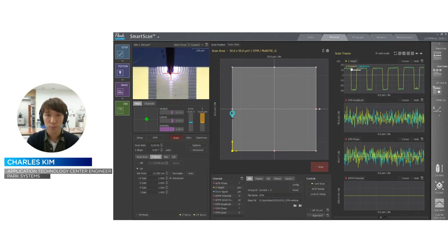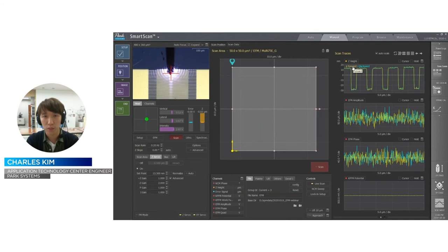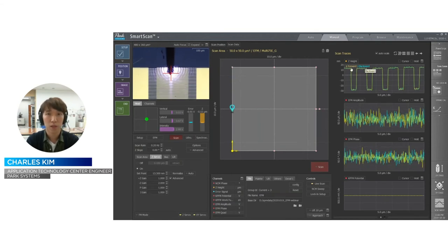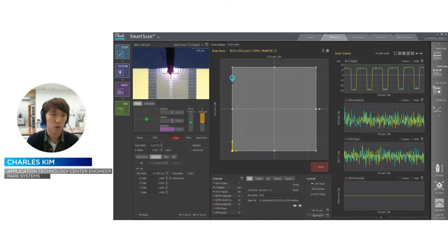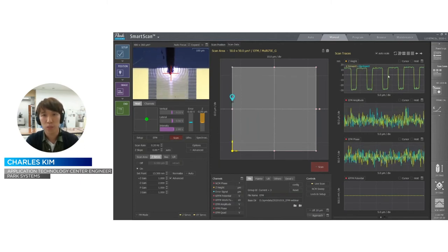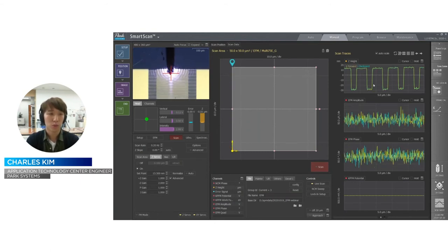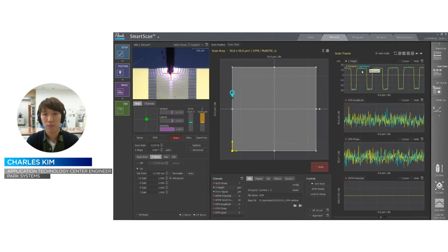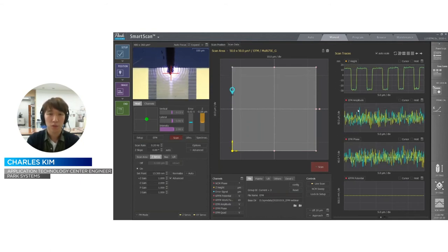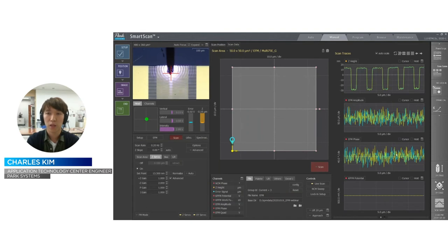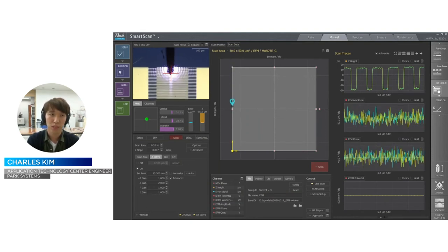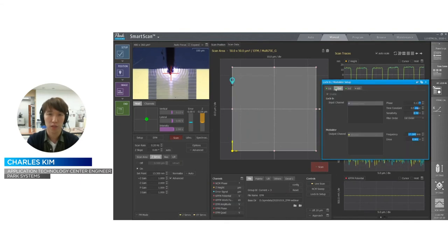And now there is the yellow line and the blue line, which are the forward and the backward lines of the AFM. The AFM actually scans the same position twice, in forward and backward scanning. So when these two signals are matched well like this, then you can say the AFM measurement is going well. So now the forward and backward lines are matching very well, so I can start the EFM measurement first. For the EFM, actually there is no signal here, as you can see. So to see the EFM signal, we need to use the second lock-in amplifier.